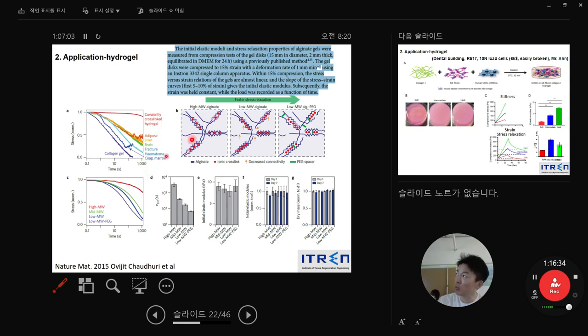That is why in this paper, they make alginate gel using different molecular weight, and then they vary stress relaxation behavior. How can we say that? Stress relaxation. They measure this half of tau. Regardless of the initial value, maybe high, middle, low, here they use the same elastic modulus, but when you measure it, maybe they can have different elastic modulus. It's okay. Anyhow, you normalize it. And then when this normalized original value at 15% compression goes down to 0.5, half, you can measure the time: how long, how fast this original stress can be half. Then you can calculate this time and convert it to half of tau.